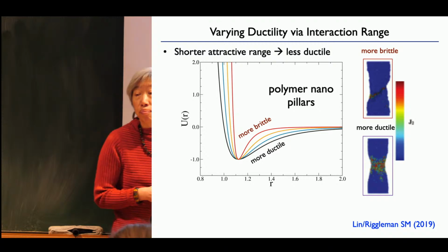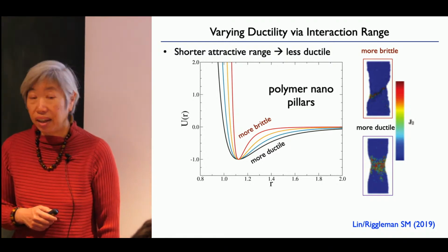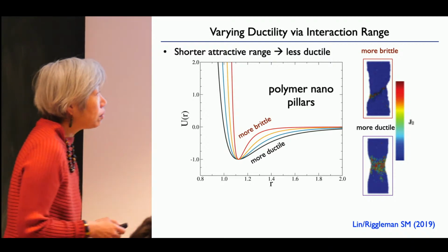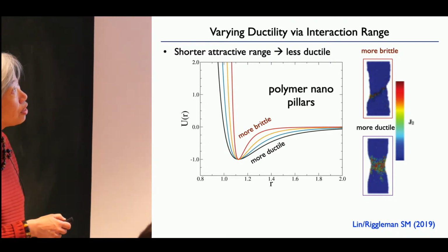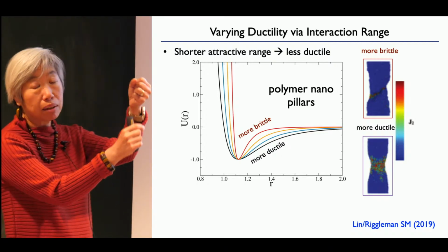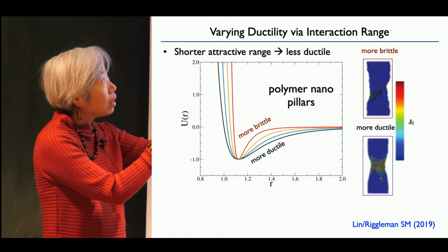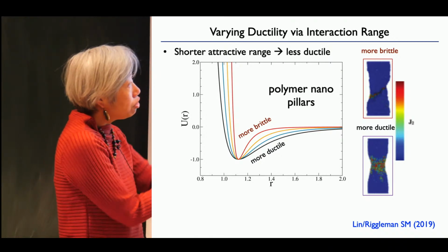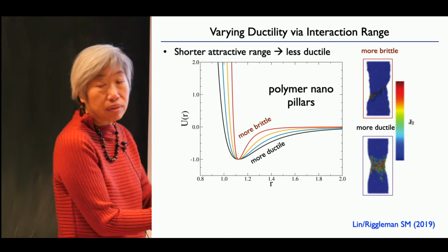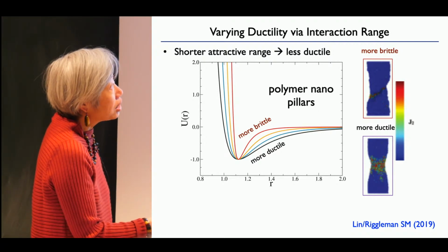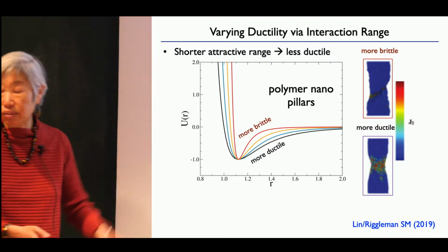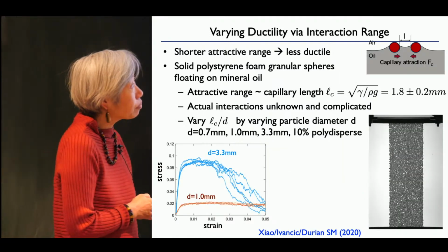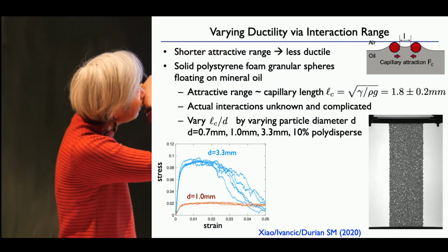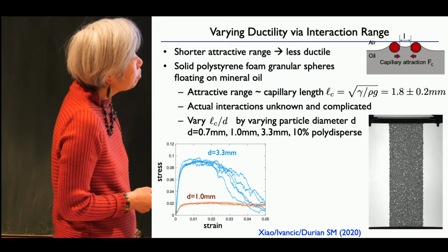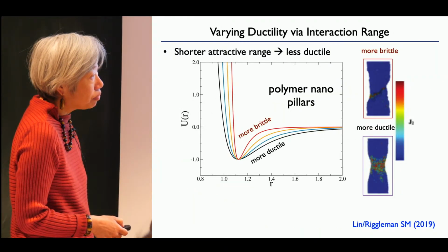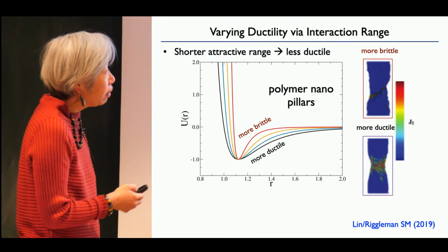And you see that the strain is more localized at the onset, when you start straining the system. So these are systems that are being pulled. These are polymer pillars that are being pulled. And you do see strain getting localized in this region where it's necking down no matter what, but it gets more and more localized as you make the interaction shorter in range. And you see a similar thing in these granular systems. I should have said the polymer work was done by my colleague Rob Riggleman at Penn.